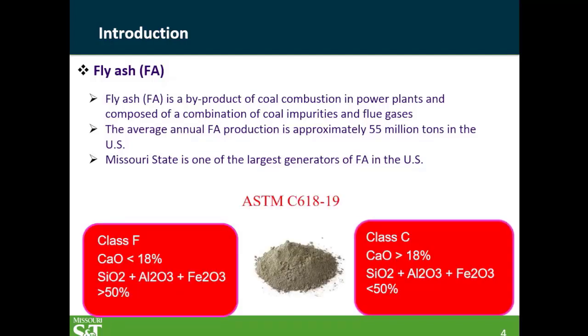We are going to focus on, per ASTM C618, two different classes of fly ash, class F and class C. Class F is basically low calcium content versus class C, which is high calcium content. What we have in Missouri, and which would be the core of this study, is class C.